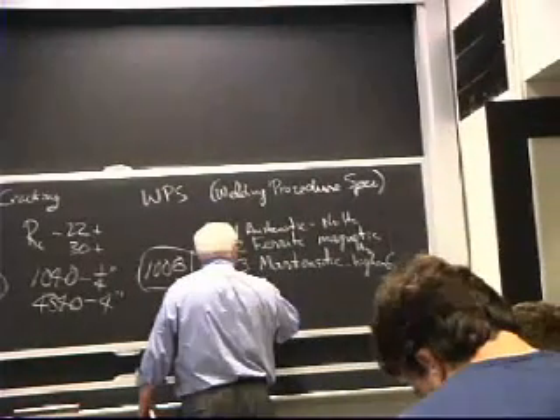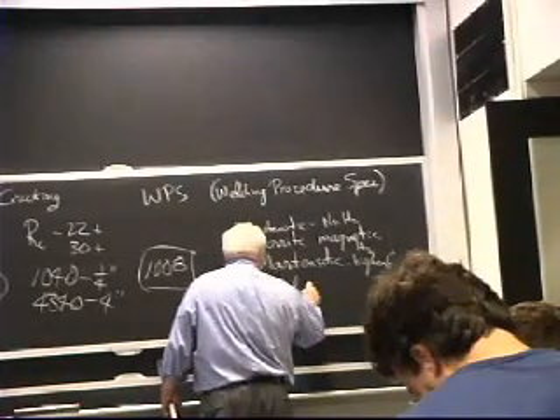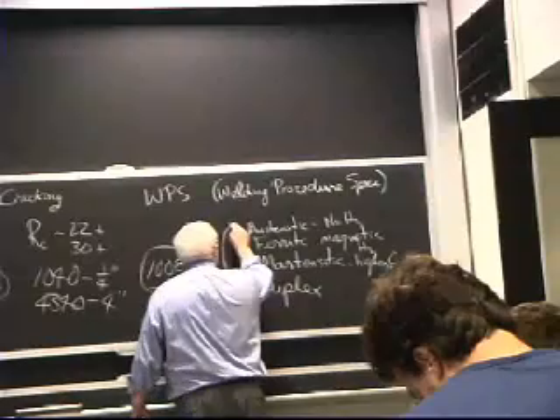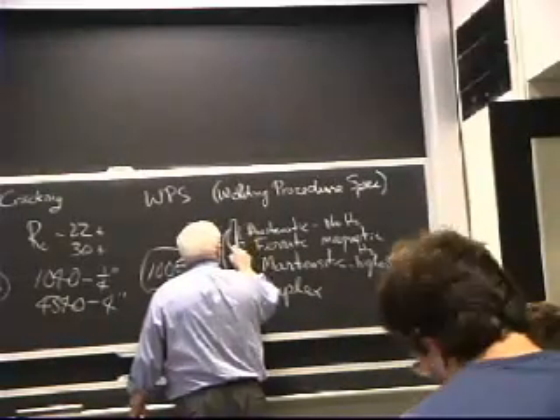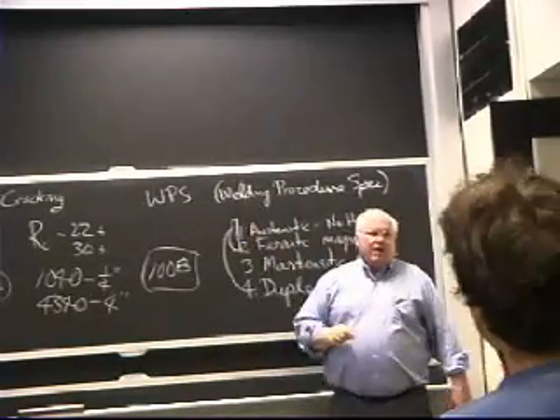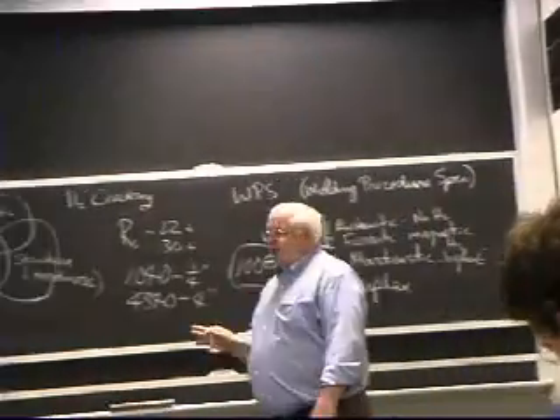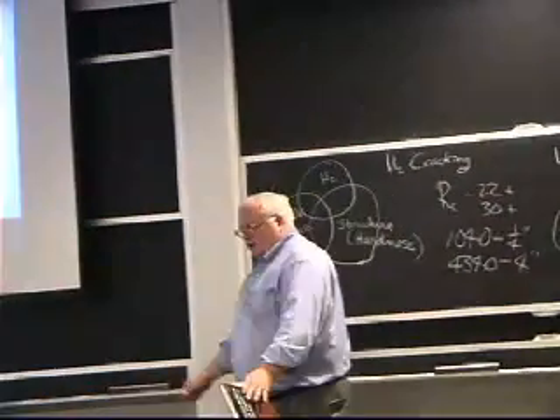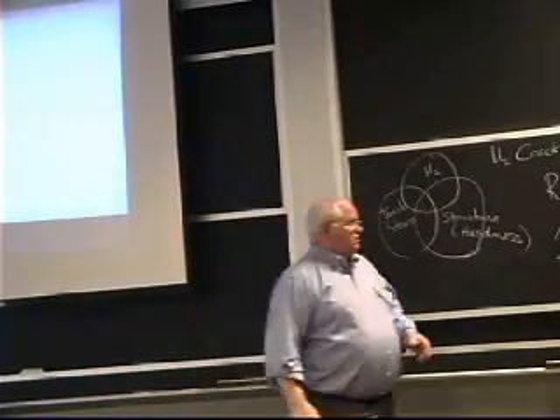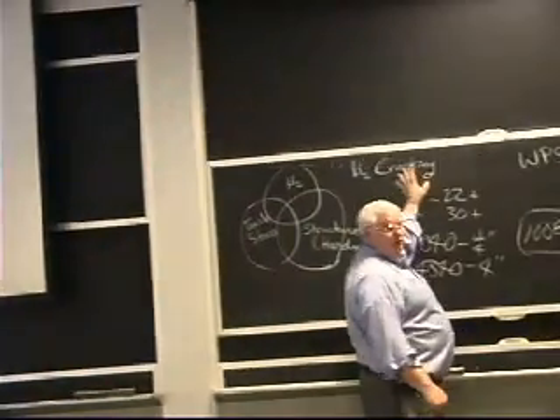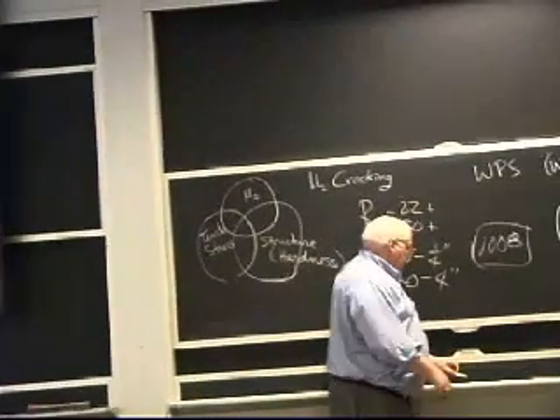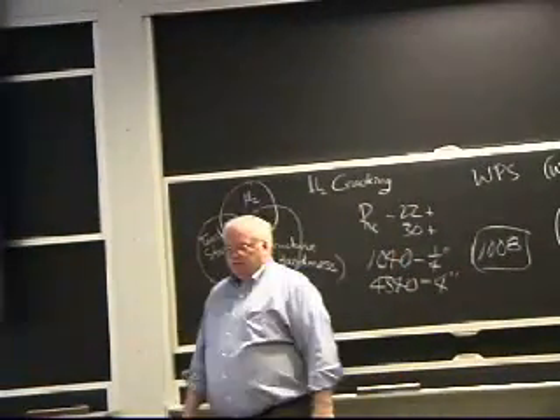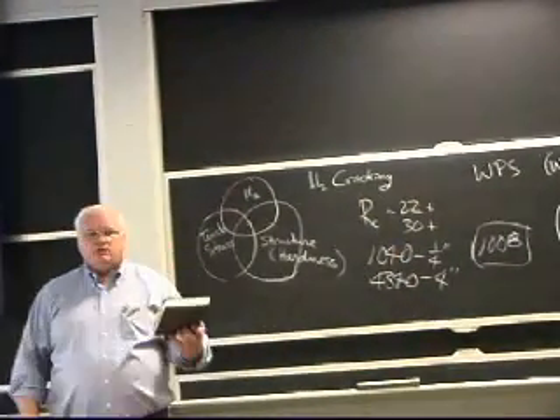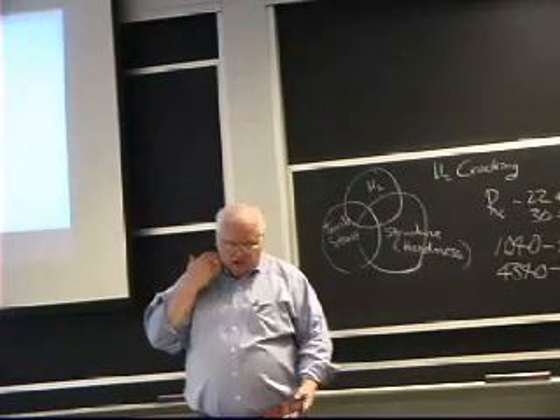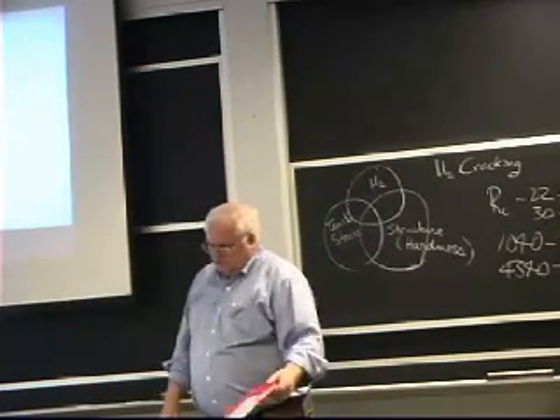And the last one is duplex, and duplex is actually a mixture of these two, right here, austenite and ferrite. It has very good corrosion resistance and high strength, particularly very good corrosion resistance in hydrogen sulfide, which is really just a form of hydrogen cracking. So you could give a whole course, and I suspect that John Lippold does at Ohio State, on welding of stainless steels.